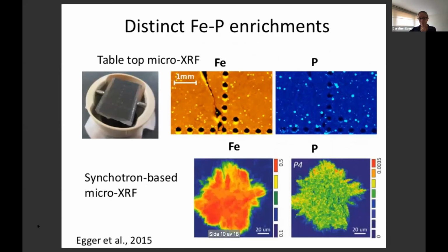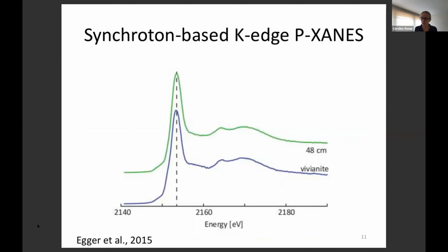Next slide. Well, to look at that, we embedded the sediment in a resin and then looked at it with X-ray fluorescence. And you can see all these little dots, all these little stars that show up at depth in the sediment. And if you zoom in further, you see that these are in fact crystals, and these are crystals rich in iron and in phosphorus. Next slide, please. And if you then use synchrotron-based spectroscopy, you can show that this is in fact Vivianite. So all of these dots that are showing up, all of these enrichments at depth, they're all Vivianite.